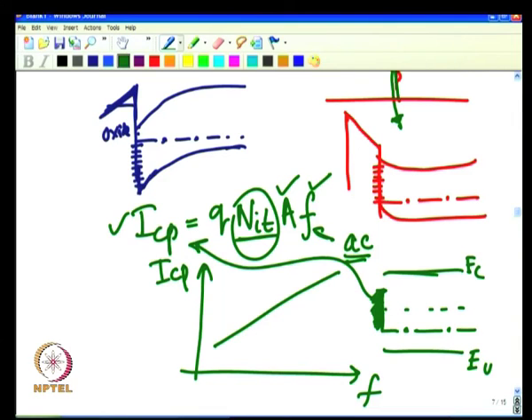To summarize: threshold voltage can be extracted using peak GM extrapolation, constant current definition, or sub-threshold to linear transition. Mobility is extracted from transconductance — the change in drain current for a given change in gate voltage. L_effective (electrical channel length) is extracted using multiple transistors of varying length with IV measurements. Finally, charge pumping is a very powerful technique to extract interface trap density from transistors.